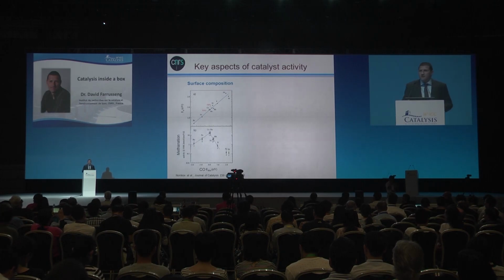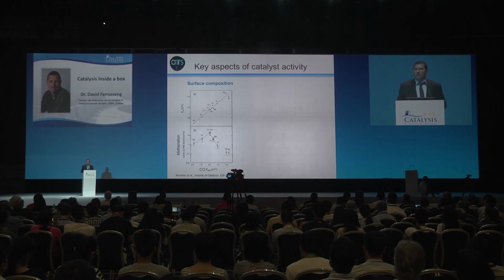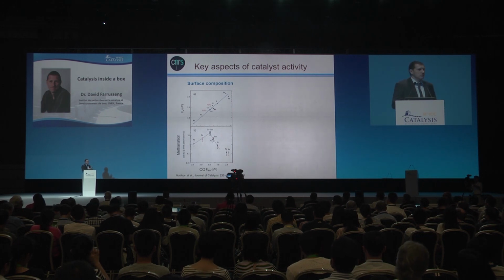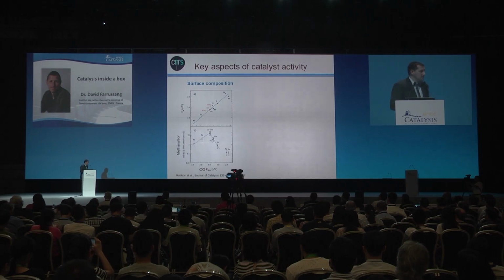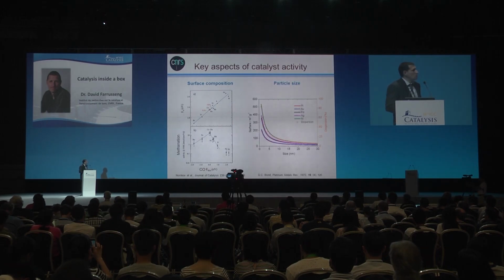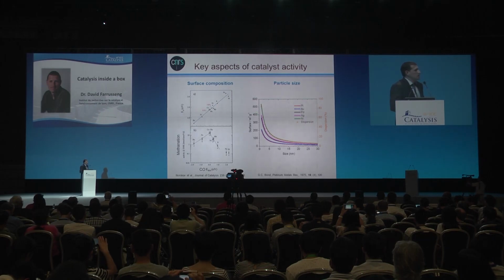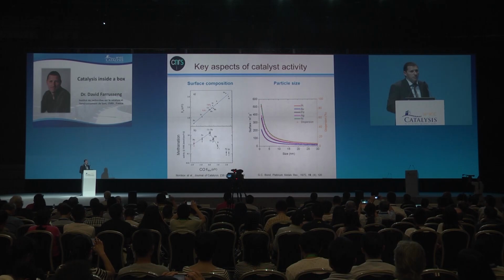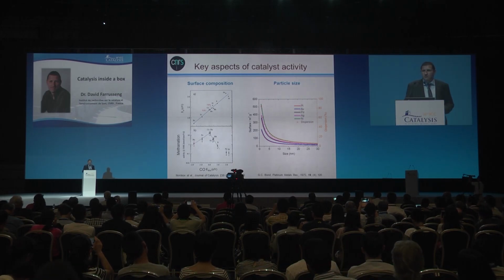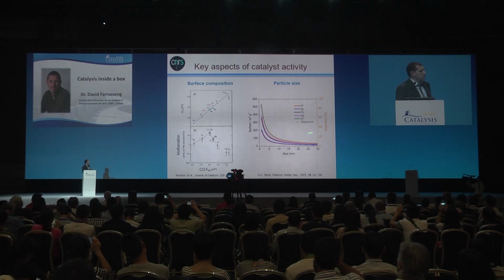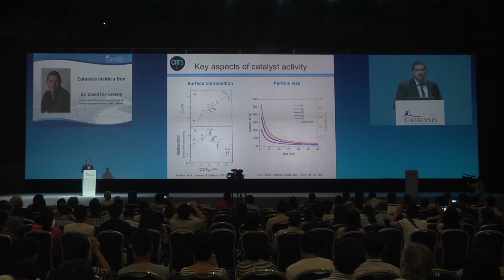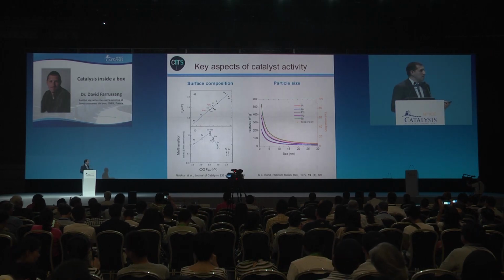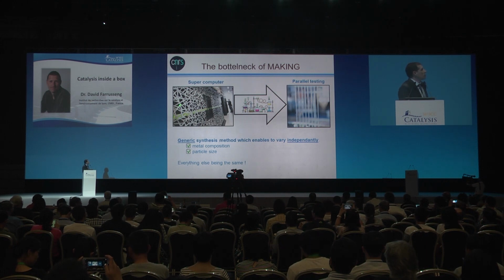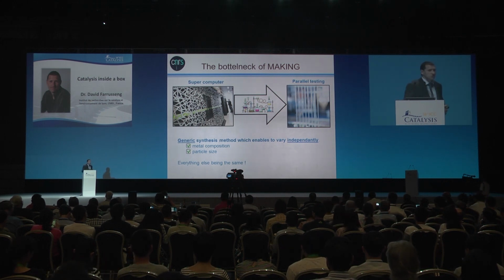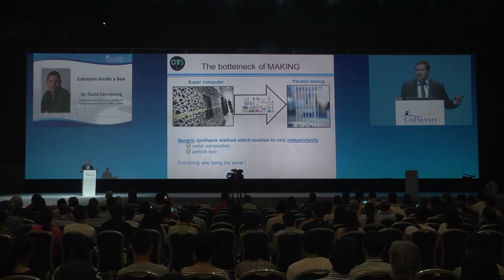The conclusion of that is we now have models and computational tools to design libraries of many catalytic candidates. So there are plenty of ideas to be tested, okay? The second point is we also know the dispersion curve as a function of the size of the nanoparticles. If you want to have a decent activity, it's better to have catalytic nanoparticles below 10 or 15 nanometers. So basically, we know how to design very active metal catalysts with the help of supercomputing and modeling approaches. So it is no longer an issue to design a metal catalyst.